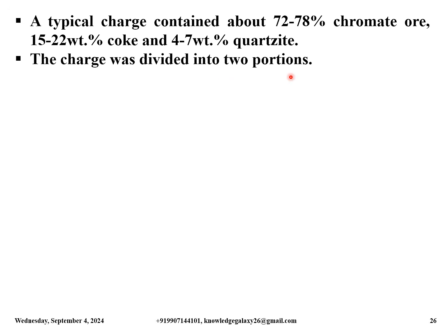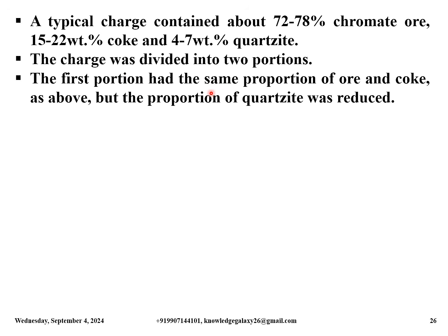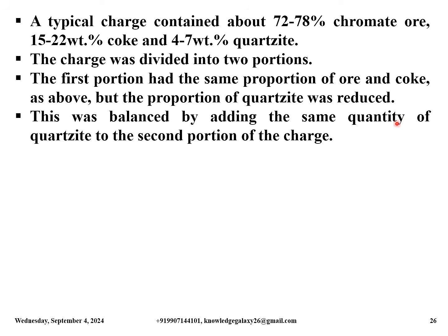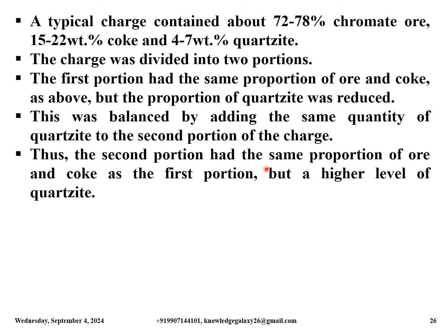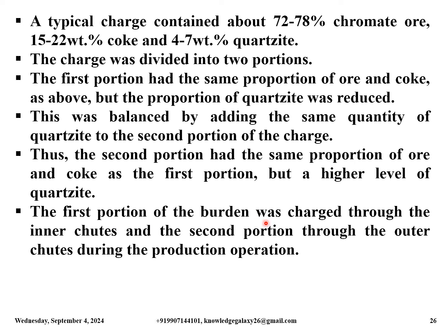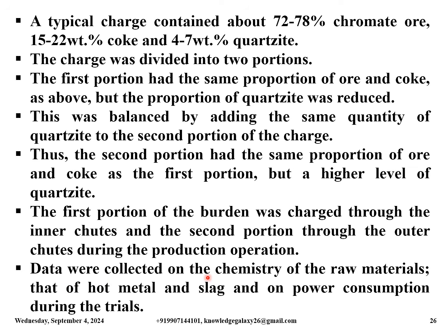The charge was divided into 2 portions. The first portion had the same proportion of ore and coke as above, but the proportion of quartzite was reduced. This was balanced by adding the same quantity of quartzite to the second portion of the charge. Thus, the second portion had the same proportion of ore and coke as the first portion, but had a higher level of quartzite. The first portion of the burden was charged through the inner chutes and the second portion through the outer chutes during the production operation. Data were collected on the chemistry of the raw materials, that of hot metal and slag, and on power consumption during the trials.